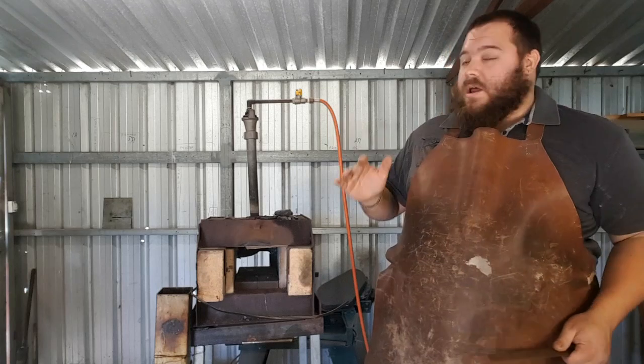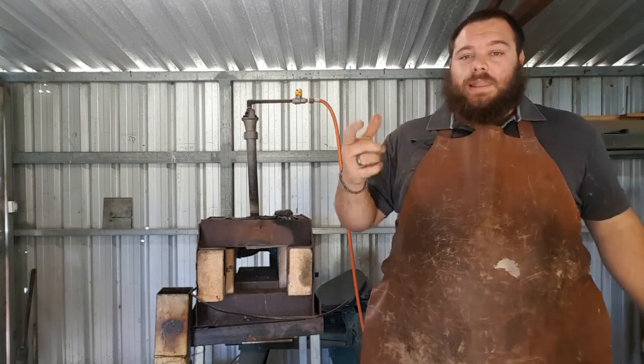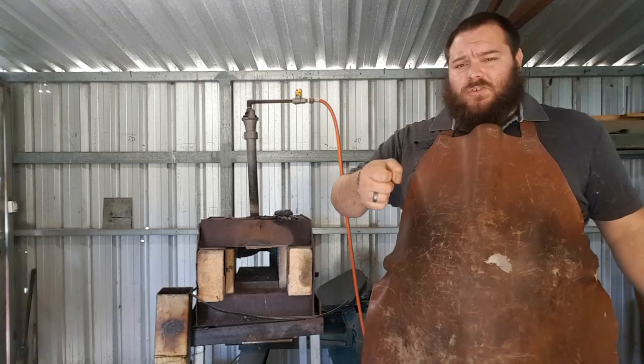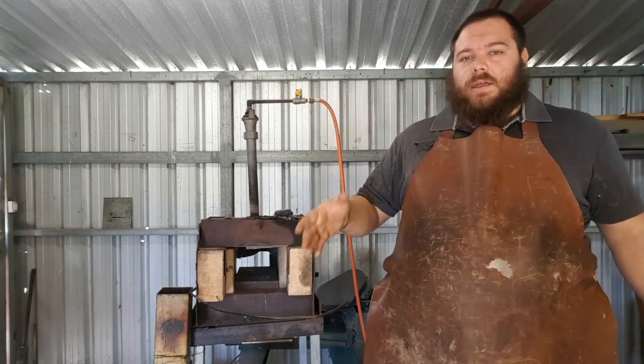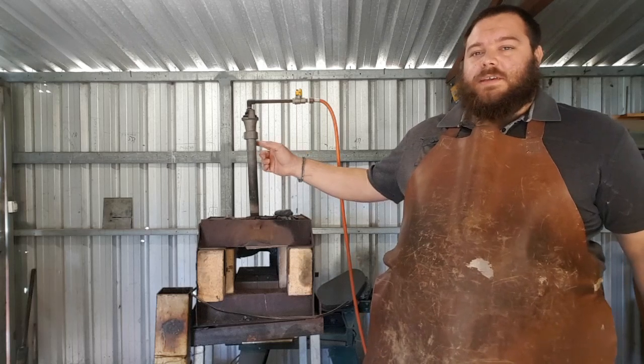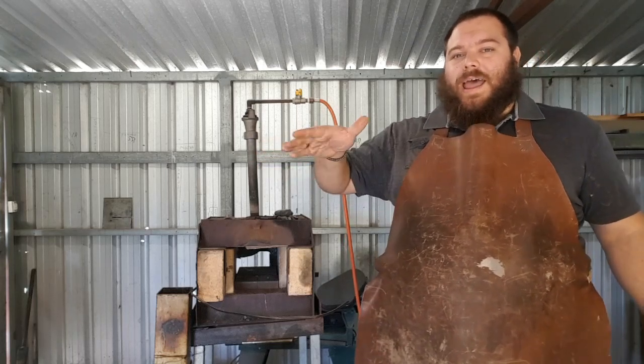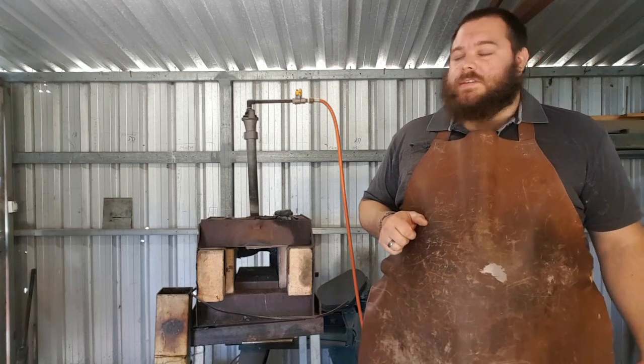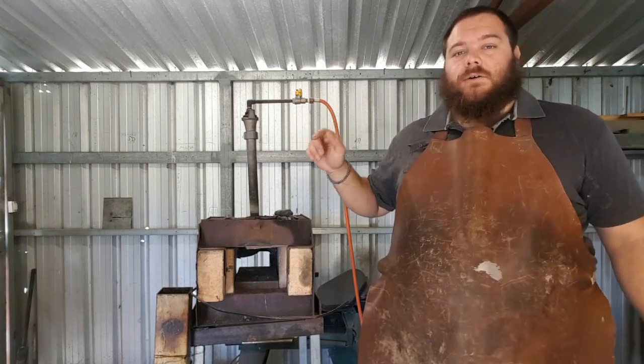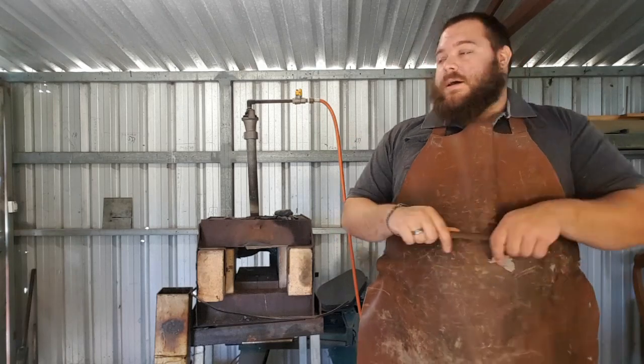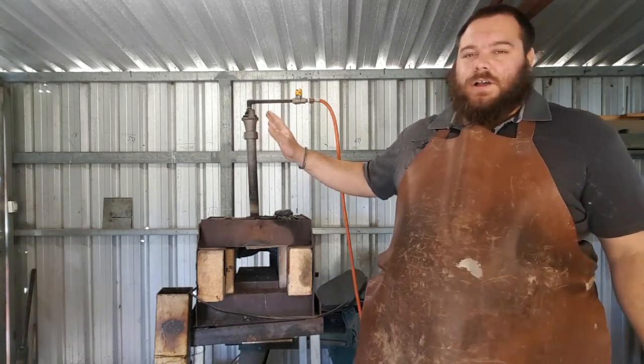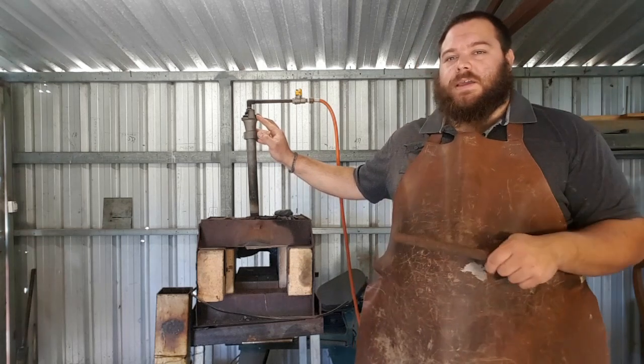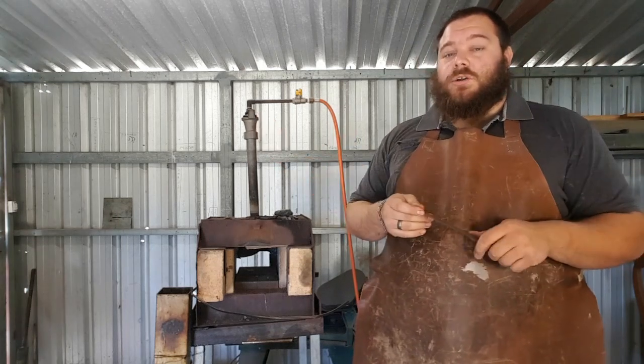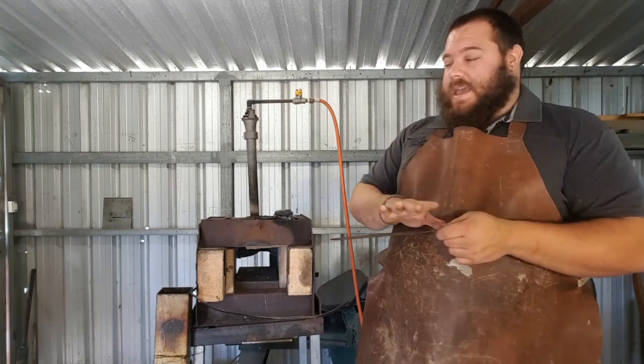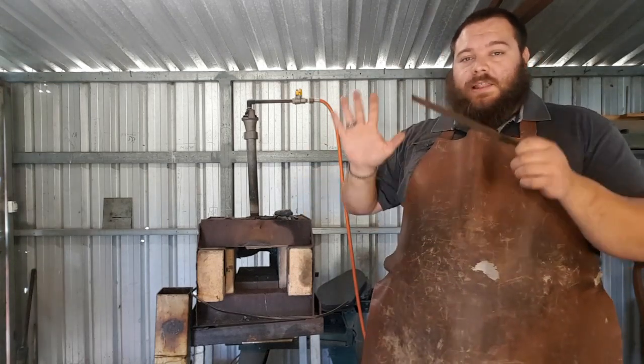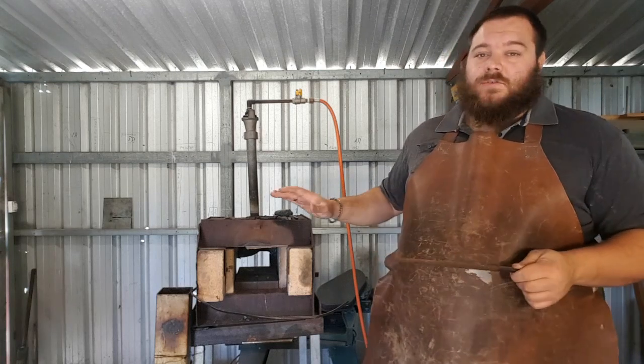How do I do it? What I've done is I had a friend who had a laser temperature reader, and basically we worked out exactly where the settings on my forge will run at about 820 to 825 degrees Celsius. And that's the settings I've got right now. So I marked that on my regulator and I marked that on my air. Sometimes I have to fluctuate the air a little bit depending on if there's a cross breeze or something. But that's how I get my controlled temperature. And all I have to do is get the steel to the maximum it can in this forge. Just sit it in there and let it go. So that's how I control my temperature.